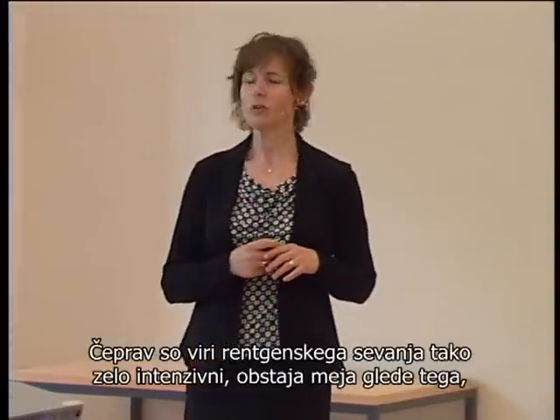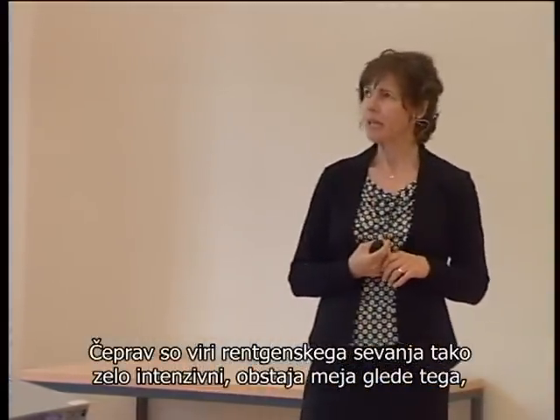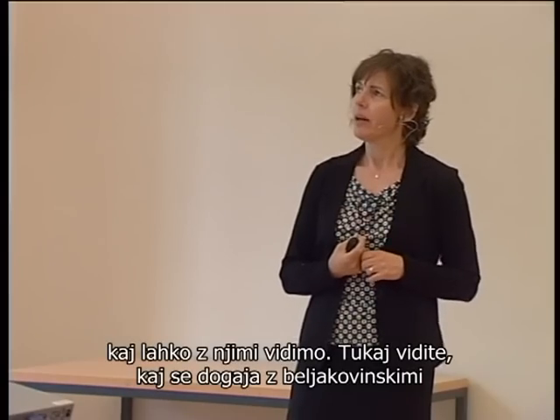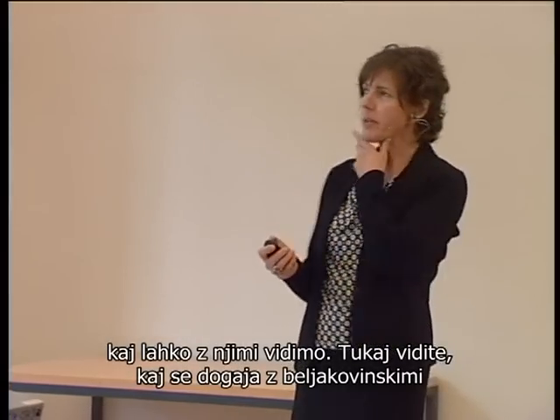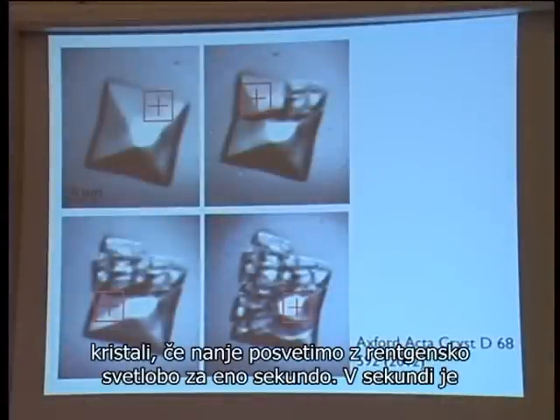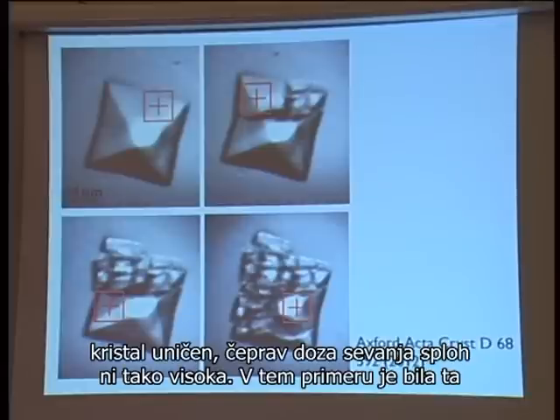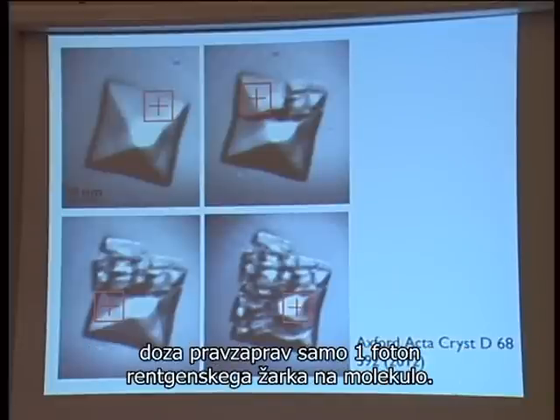So what next? What I wanted to say is that even though these X-ray sources are so intense, there is a limit of what we can see with them. Here I'm showing what's happening with the protein crystals. We shine X-ray light on the protein crystal, for example in this position, for 1 second. You see it's destroyed. Wherever we shine, within a second, the crystal is destroyed, even though the dose is not so large. Actually, the dose is, in this case, only 1 X-ray photon scattered off per molecule.